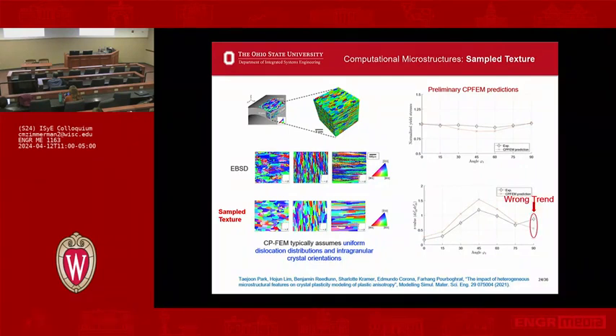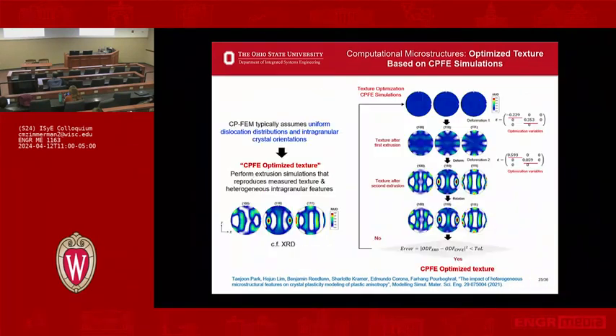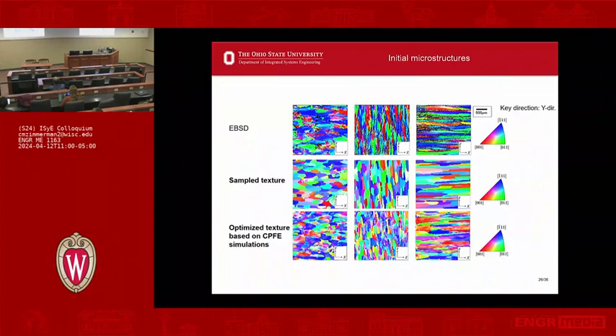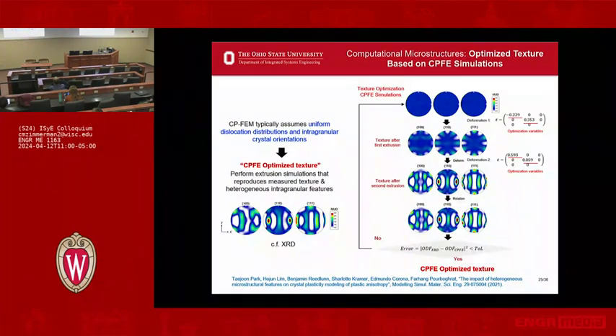So what we did, we created an optimization model of this. We said any material before it became a tube must have been completely isotropic. They measured this thing at the end when it was already a tube. They didn't know anything in between. But we understood what an extruding process is, so we created an optimization process: if it starts from here, what parameters of deformation must it have gone through in order to get the final one, which is here. So we did an iterative process to figure out the parameters of deformation.